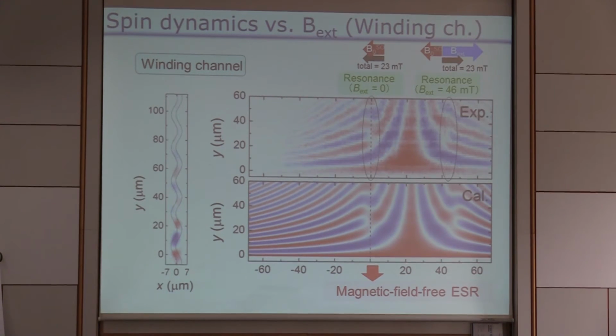Yes. So these experiments are made with an ensemble of spins. Do you think you can go down to the single spin level? Yes. We want to do that, but to do that, we need to make the size of the dot smaller. In this experiment we have a lot of electrons, maybe from 100 to 1,000 in one moving dot.